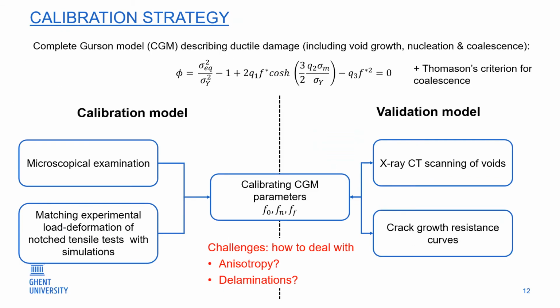For the ductile damage model, we will make use of the complete Gurson model, defined by the yield criterion of Gurson, Tvergaard and Needleman, complemented by the void coalescence criterion of Thomason. The model has some parameters that need to be calibrated based on microscopical examination and the matching of the previously shown experimental load deformation curves with numerical simulations.